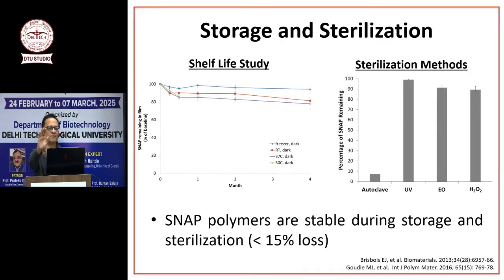Okay, so this is your question, Neha. We did a shelf life storage study. Actually, we even have 6 months of data now. I just didn't put that data here, but we have 6 months of data on how much NO we are losing in the freezer, in the dark, at room temperature, and at 37 degrees Celsius. But it's all in dry conditions. So we lose less than 15% of NO. And actually with the newer materials we have, in the 6 month data, we are losing only less than 10% of NO in storage during shelf life.